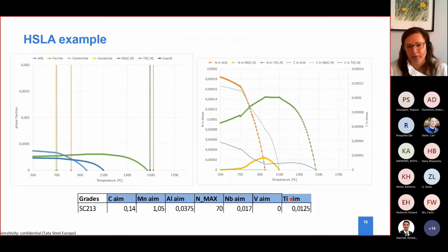In the example, so what happened? We have a chemical composition that is somewhat peritectic. We have quite some manganese. Aluminium is added for the deoxidation, but we need to take it into account also, because at least a quarter of the aluminium added, even for the deoxidation of the steel, could bond with nitrogen, because we have quite some nitrogen. This is at ppm level. And then we have some niobium and titanium in this steel.